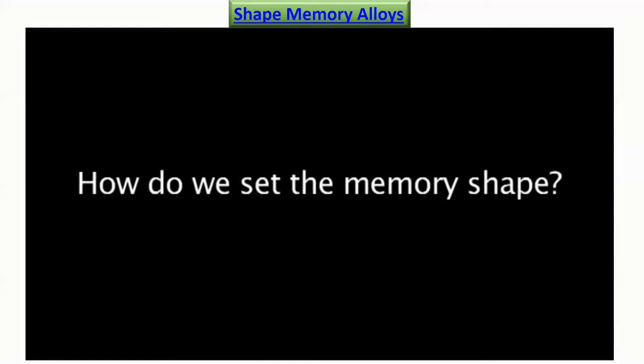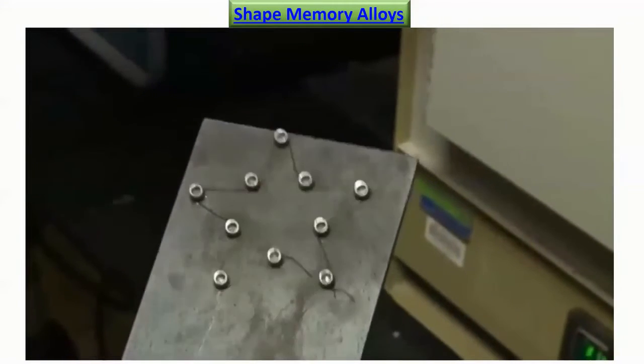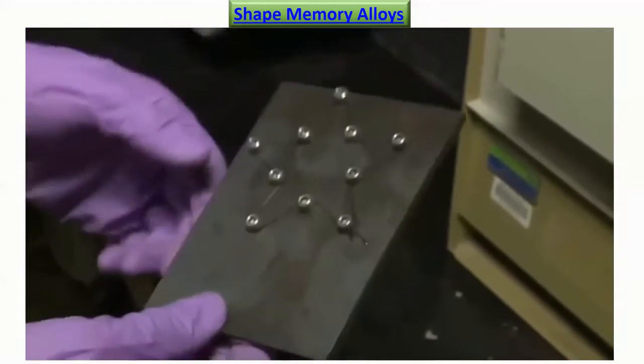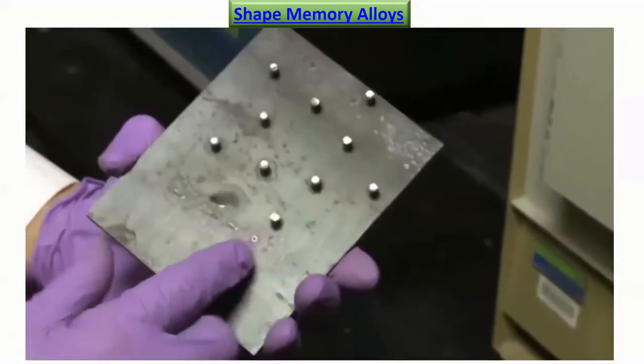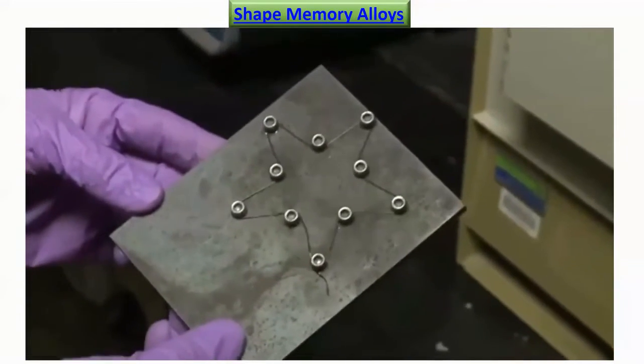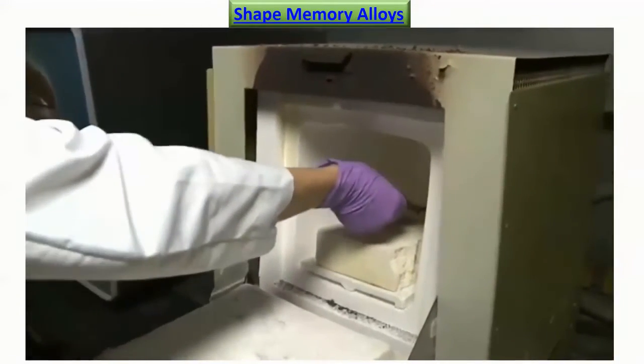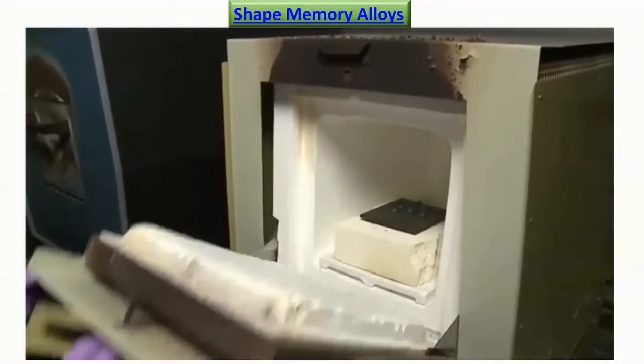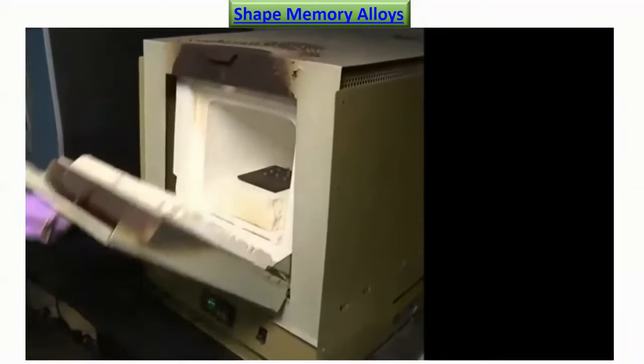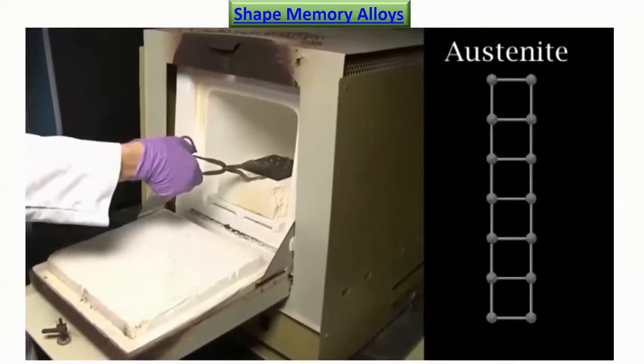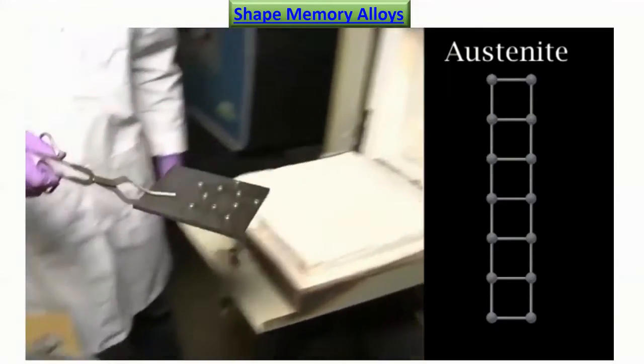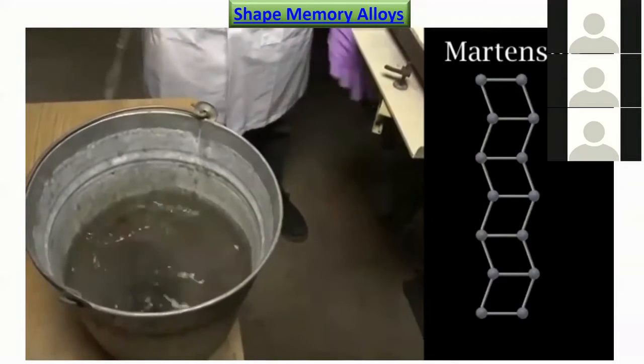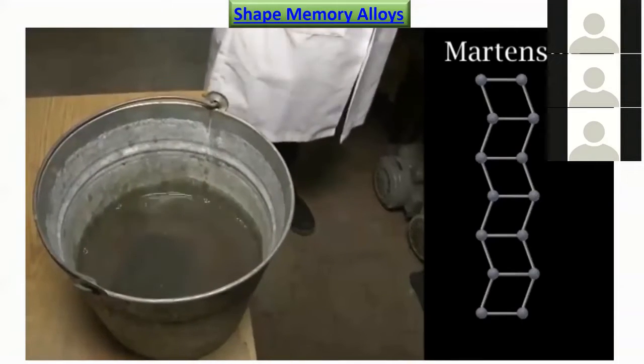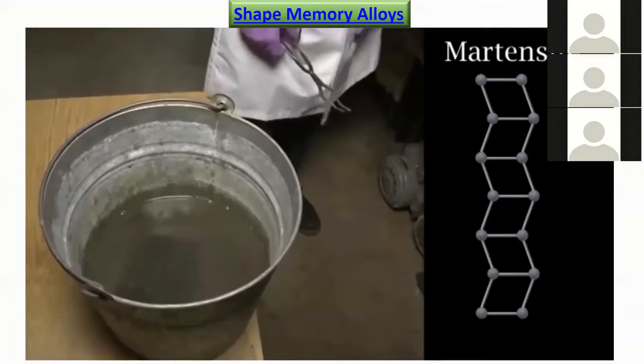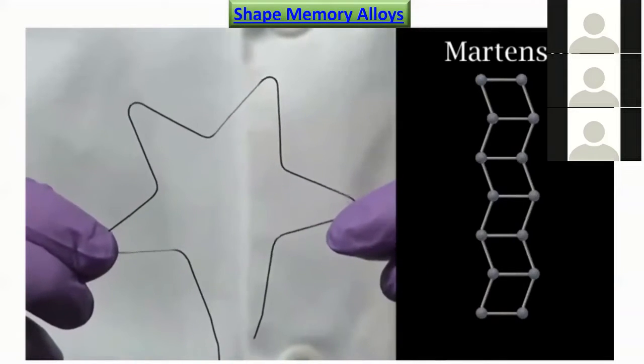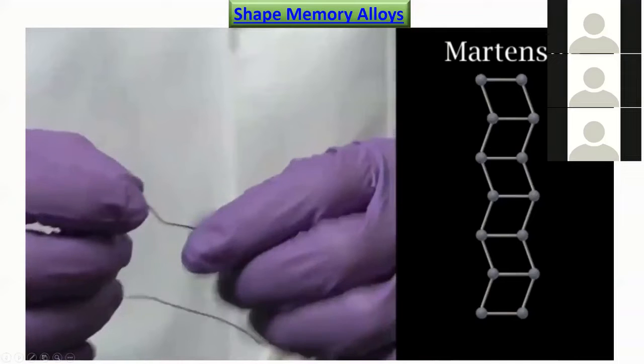How do we set the memory shape? To set the shape that we want, we must hold the material in the austenite phase at high temperatures. Here, we have used screws to hold the wire in place on a metal plate, which we then put into the furnace to heat it. Inside the furnace, the wire transforms into austenite, which sets the memory shape. When we cool it down, it transforms into martensite, but it does so without changing the shape. In the graphic, you can see that the atoms have the martensite structure, but they align in a zigzag pattern, so that the overall shape